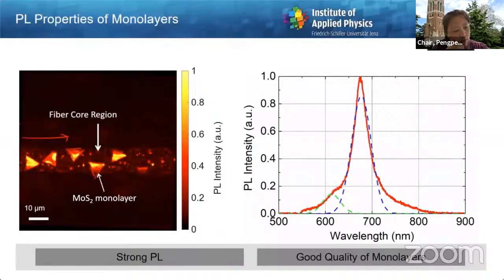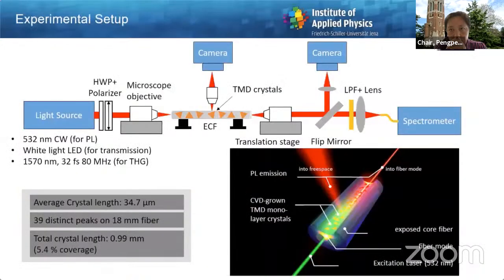And if you take a spectrum here or there, then you typically get curves which look like that, which are pretty much identical to those from the monolayer crystals on the bulk surface. Peak at 670 and full width at half maximum of roughly 40 nanometers. So basically, you see strong PL and good quality of the monolayers. Now we're good to go to actually do in-fiber experiments. We take a light source, we focus the light source into the optical core, we propagate light down.